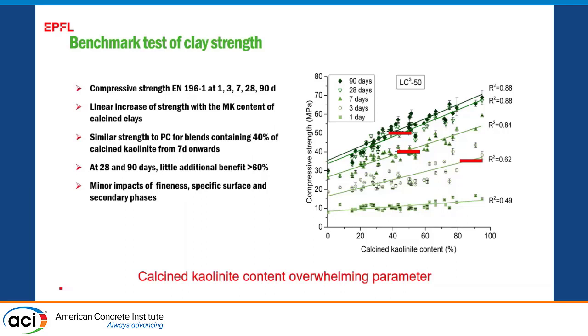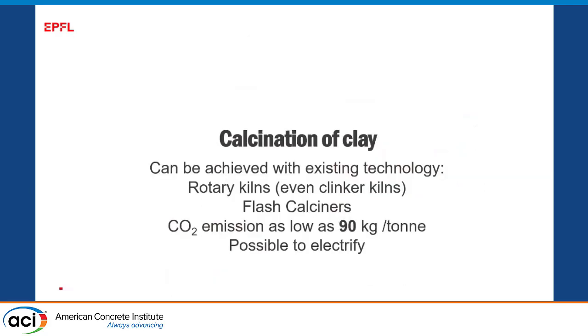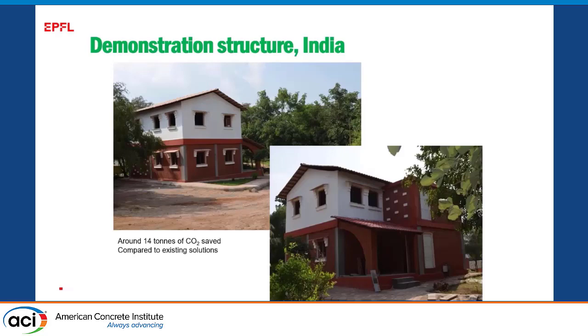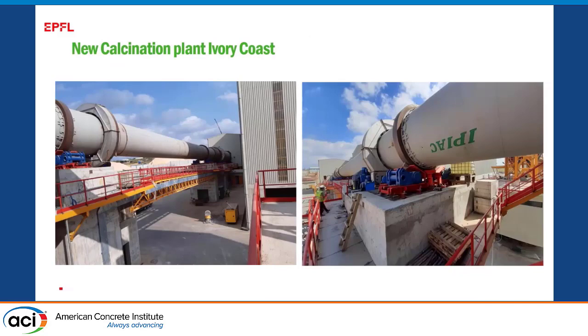But often the kind of clays we can use in LC3 are found as waste from those other industries because the grading, the content of kaolinite, is too low for those applications. We've got existing technologies ready to go today, which can do the calcination with emissions as low as 90 kilograms per ton. So that's about 1/10 of the emissions of clinker. And we've taken this to full scale, built houses out of it. There's already existing plants, such as this one in the Ivory Coast.